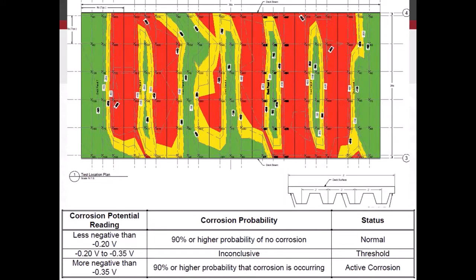Obviously, these results are significantly different, but not surprising considering some of the photos that we saw. Right, a lot of rust stains and corrosion byproduct. And if you look at where a lot of these red areas are, it's right in between the joints, right? So the water's getting right in between the joints. Not sure how they were sealed up, or if they were even sealed up very well at all. But certainly the corrosion is happening where we would expect it to happen, just not necessarily to this degree.